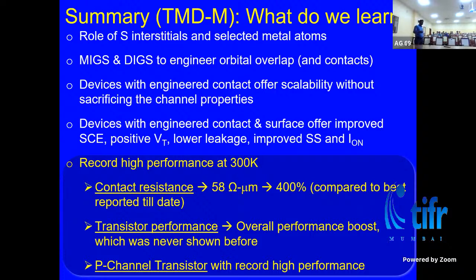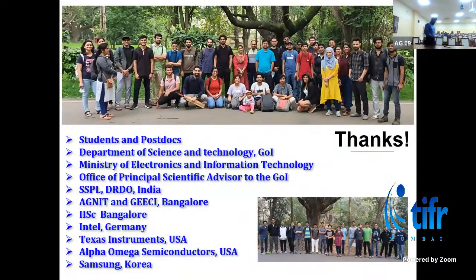So in terms of contact resistance, we reported 58 ohm micrometer, which is 400% better compared to any number reported in literature. Transistor performance, we demonstrated overall performance enhancement because we not only improved the contact, but also improved the channel property. We passivated those sulfur vacancy defects, which were making it intrinsically N-type, which we don't want. And we also demonstrated a P-channel transistor as a function of the same engineering approach, or the orbital overlap. On this note, thank you very much, and I'm open to your questions.